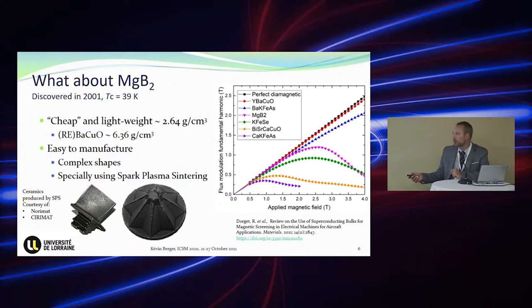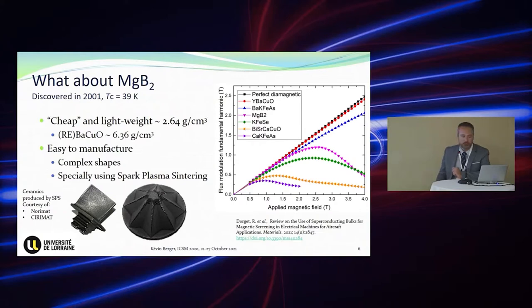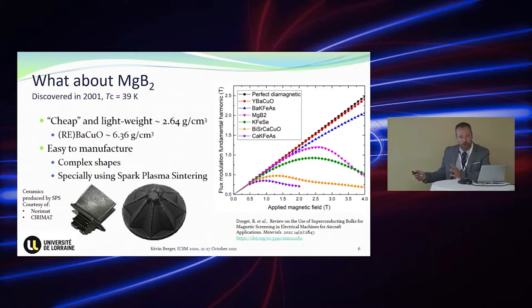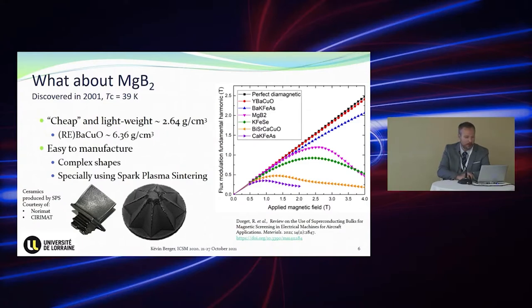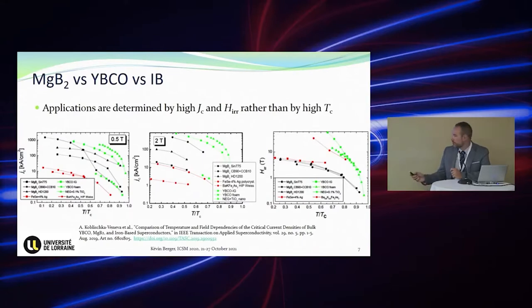On the bottom figure, you can see ceramics built using SPS — you can see how complex the shapes can be and what we can aim for with MgB2 samples. In a recent review, we compared the performance in a machine of several typical bulk materials. Of course YBCO is the best, but you can see some challengers — iron arsenide and MgB2. In the range of 2.5 T applied field, which is almost the optimum we can produce in a typical machine, MgB2 is a good challenger.